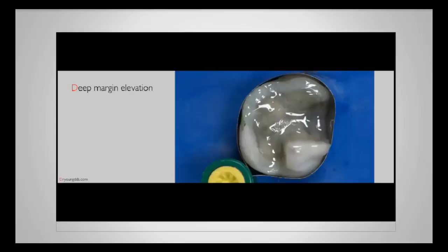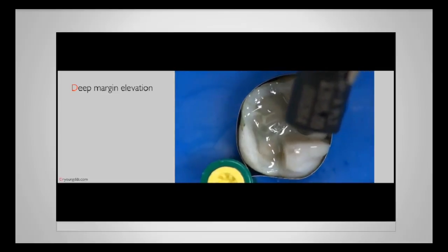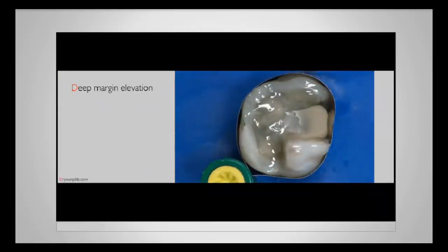So what we do is we basically now, we've done our immediate dentin sealing, we've locked the flowable down there at the bottom of the matrix, so we're simply going to come in with APX in this case, because that's the material that I like for this. It flows so nicely, yet it has a high compressive strength to support enamel or your restoration on top. It goes where you want it to go when you pack it. And so we push that into position. Again, you could do it in your 1 or 2 millimeter increments here.